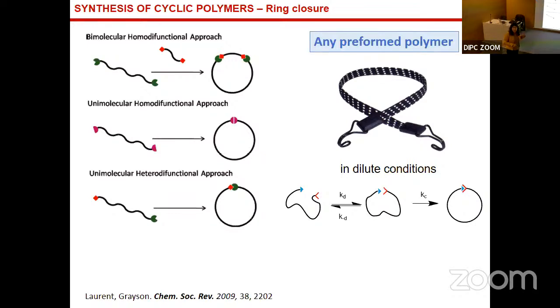The problem here is that we have to work in highly diluted conditions, because the end groups have to find each other, and this is entropically very difficult. And also to avoid that two linear chains, for example, find each other and react between them. So what we want is that the end groups react against each other. And this is limited by diffusion and by the kinetics.